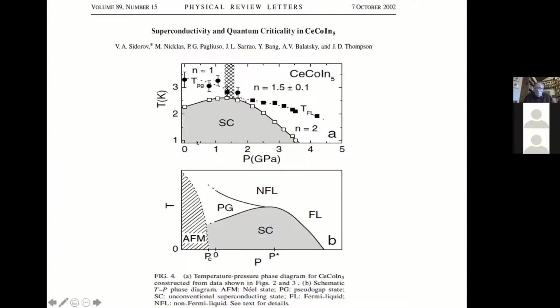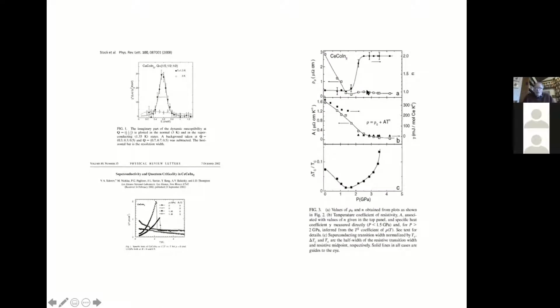The interesting thing here, to me, is that you actually have an increase in TC from about 2.3 Kelvin to about 2.6 Kelvin, somewhere around 1.5 gigapascals. Now, what happens when cerium cobalt indium 5 goes superconducting? In this diagram over here, this is data from Stock and Broholm, there's this neutron resonance that develops when one passes through the superconducting transition temperature. In other words, some of the magnetic fluctuations get gapped out when cerium cobalt indium 5 goes superconducting.